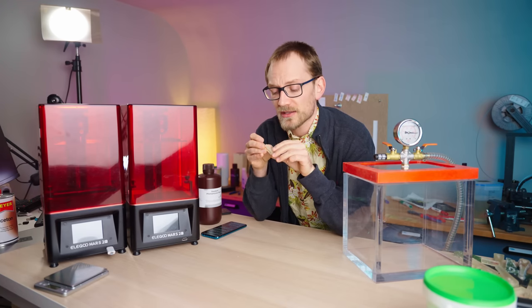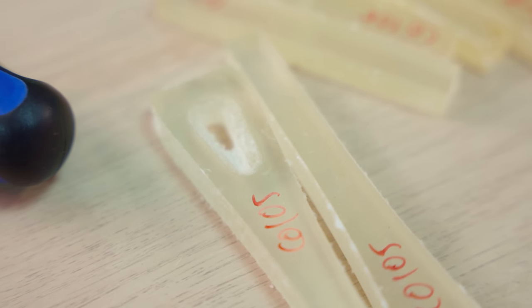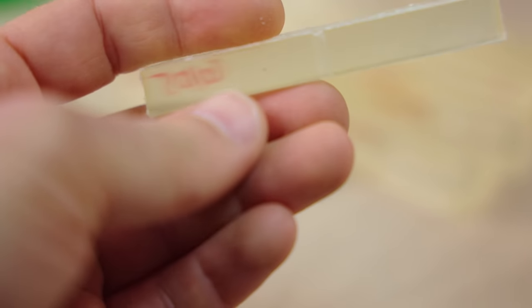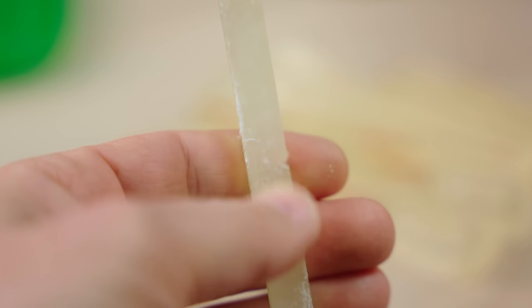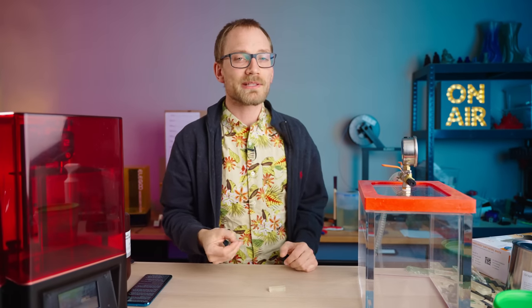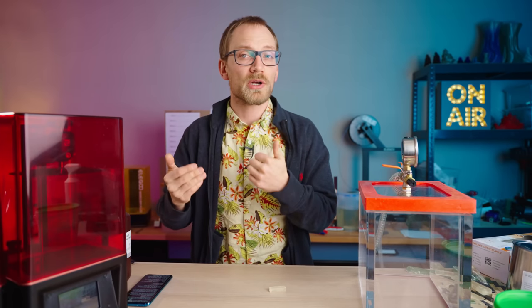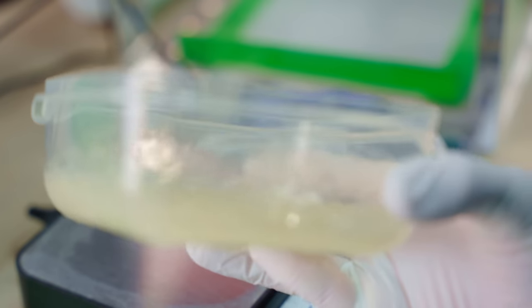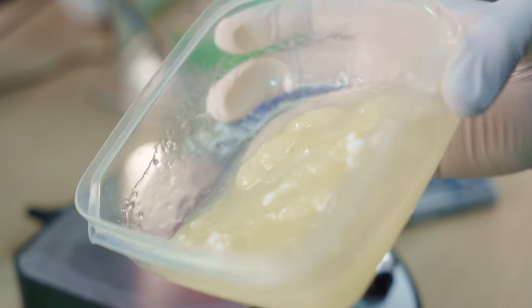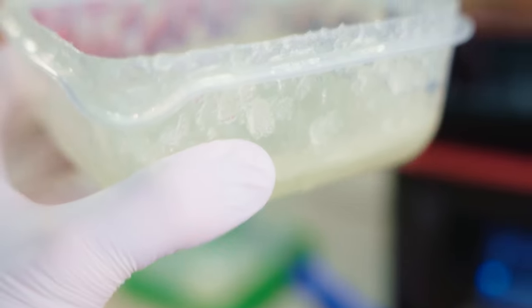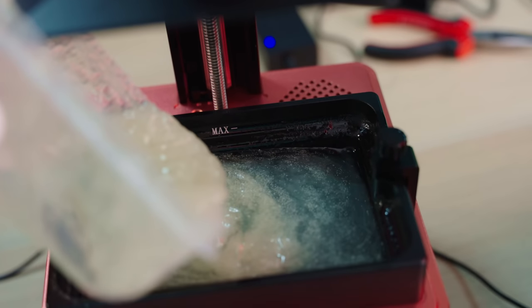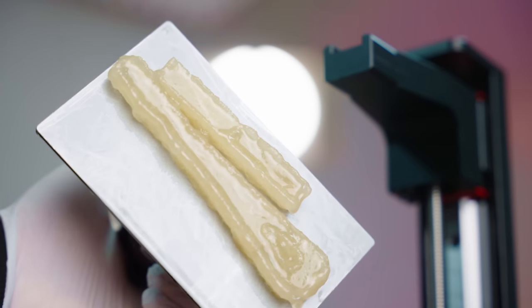There was still a bit of fluff left on the cotton parts, but that is very easily rubbed off, and actually it kind of makes the parts feel soft, which I do actually like. But in the case of cotton, if you needed to get rid of these, you could probably just burn them off with a torch or something. After that, I continued on with the cotton experiments and just reused the resin and added more and more cotton to it until I felt there was a point where it might not be printable anymore. That point, for me, felt like it was around 1.5% by weight, and at that point, you can definitely tell that there is stuff added to the resin and it's not really flowing that well anymore. It wasn't turning into this nasty glue or slush at this point yet. In all cases, the cotton reinforcement seemed very evenly distributed throughout the parts still.